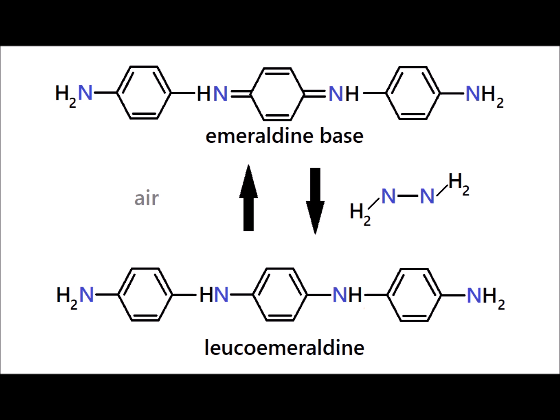If we want to go in the opposite direction — from emeraldine base to leucoemeraldine — then we use something like hydrazine or phenylhydrazine, which is a sufficiently strong reducing agent to reduce it from emeraldine to leucoemeraldine.